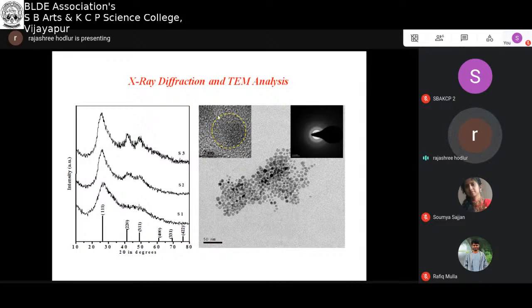So here you can see this is the TEM image of cadmium selenide quantum dot, and the scale that we have measured it in is 2 nanometers. So here, even when the material goes into the nano region, the intrinsic property is still retained. So using transmission electron microscopy, we analyzed the crystalline property of cadmium selenide quantum dots.